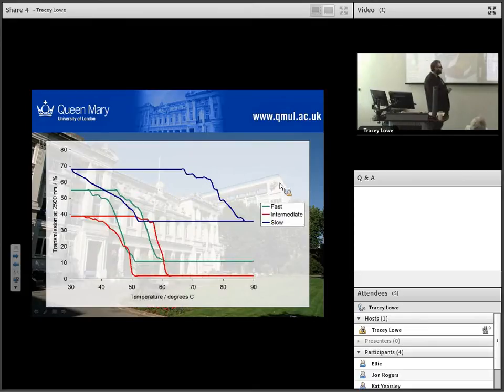And as a result of that, we see some changes in our hysteresis behaviour. For example, the films which have grown very slowly have got this very wide hysteresis, and it's quite a slow transition. If we take the midpoint of the biggest change, our transition temperature is something like 65 degrees centigrade. If we take the contrasting example where we've grown it quickly, the transition width is much narrower, the gradient is a little bit sharper, and also our transition temperature has been reduced.